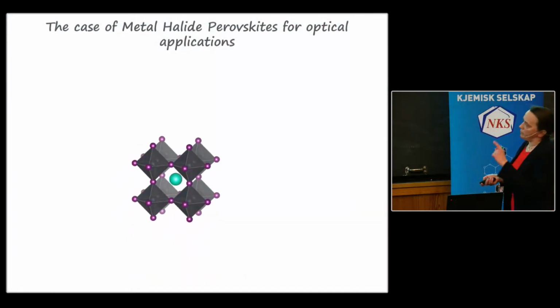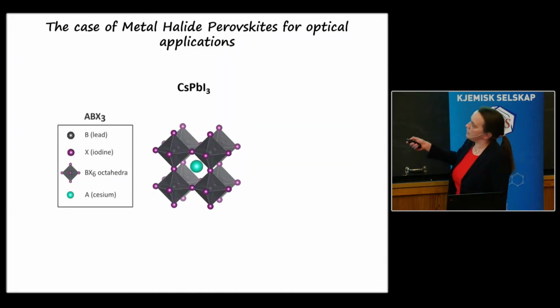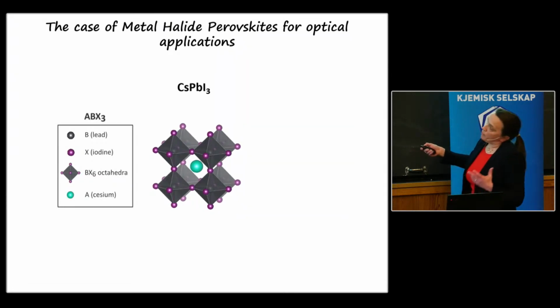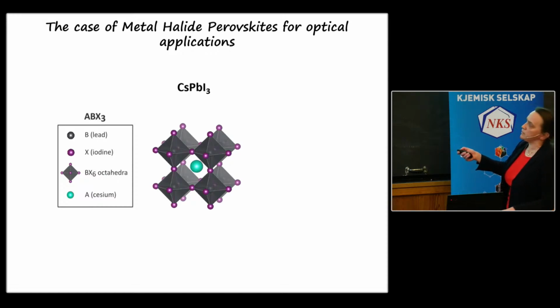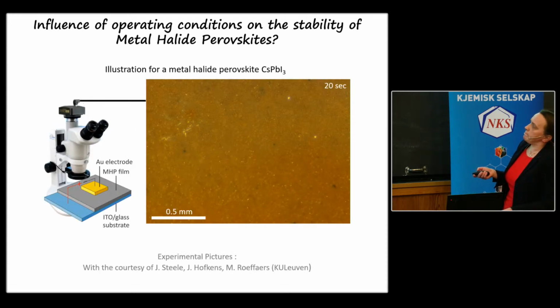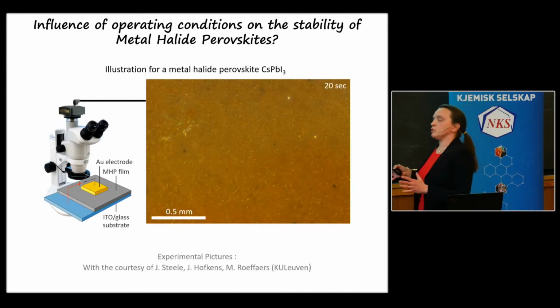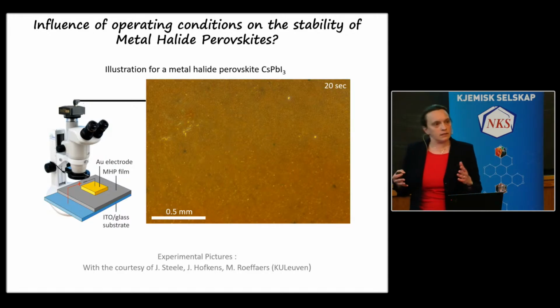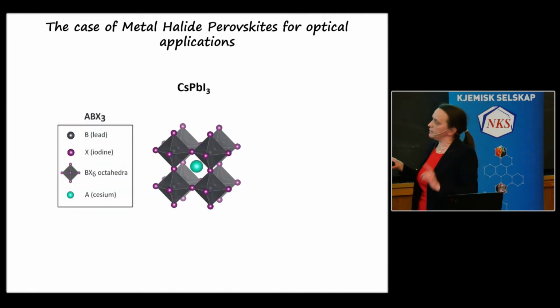Now we are going to look at what they look like on the nanometer scale. Perovskites have this ABX3 structure. In our case, this is cesium, then we have lead here, and this is iodine. The purple things are iodine. So you can see it's a very well-structured material with octahedrons. We are going to use them in optoelectronic devices, and the interesting thing is that when this material has this form, with these octahedrons, then it's optically active.